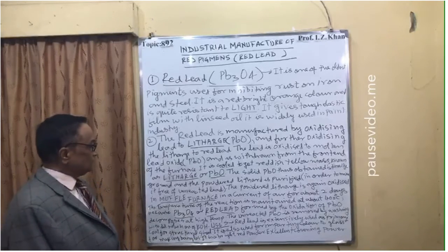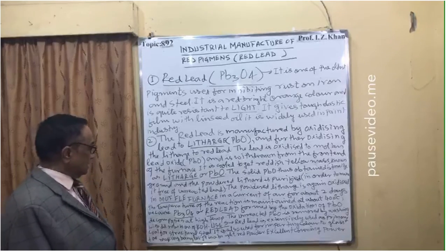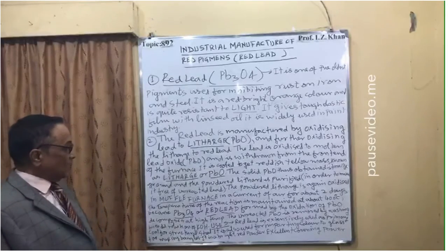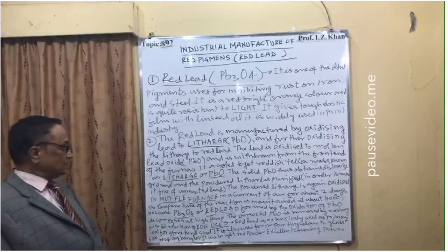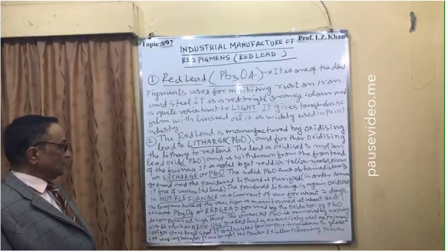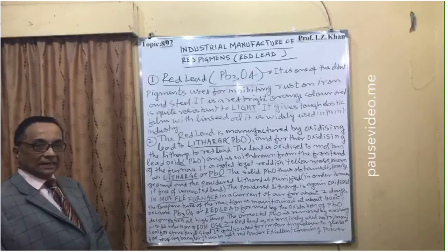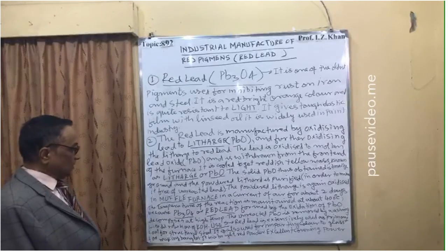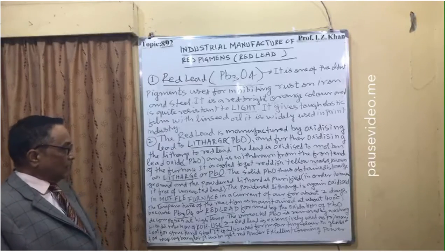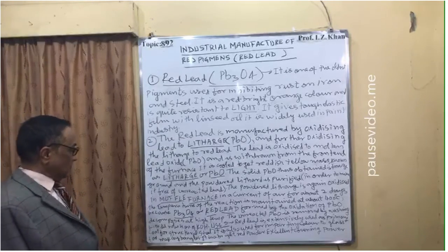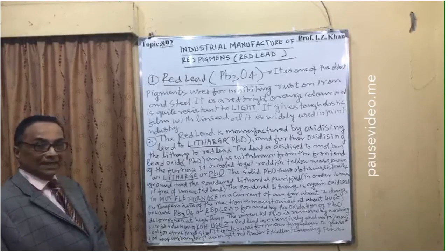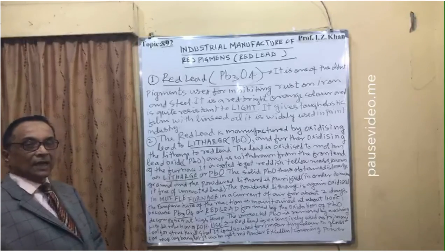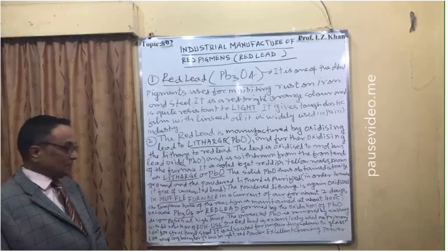The powdered litharge is again oxidized in a muffle furnace, a special type of furnace, in a current of air for about 2 days. The temperature of the reaction is maintained at about 400 degrees centigrade, because Pb3O4, or red lead, formed by oxidation of PbO decomposes at high temperature. The unreacted litharge, PbO, is removed by washing with dilute potassium hydroxide KOH solution.